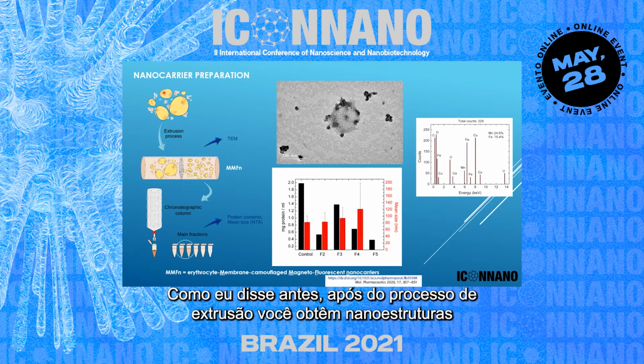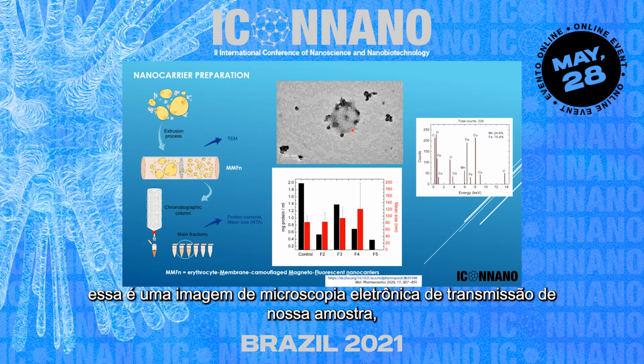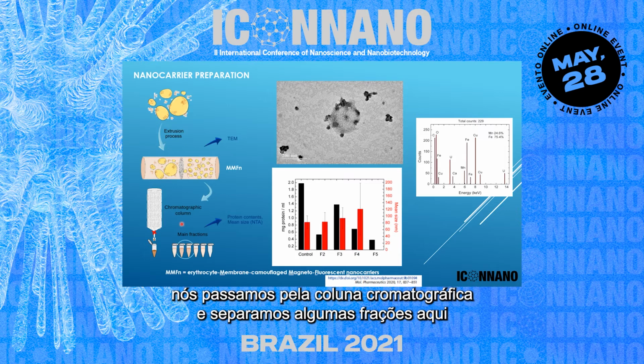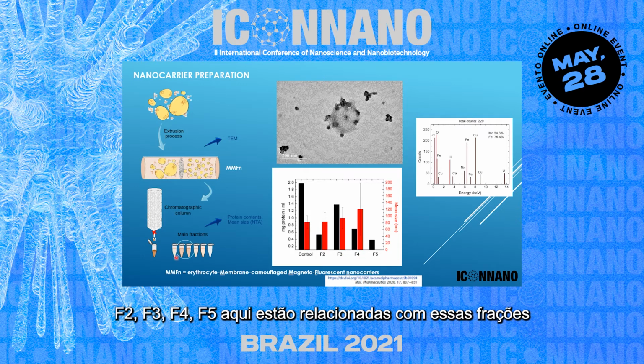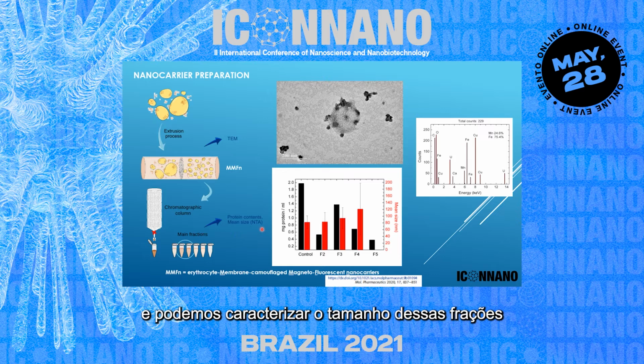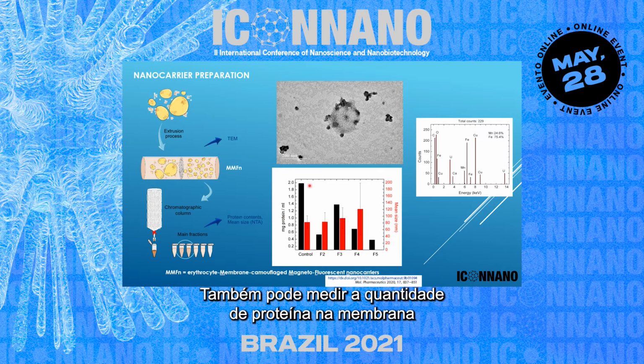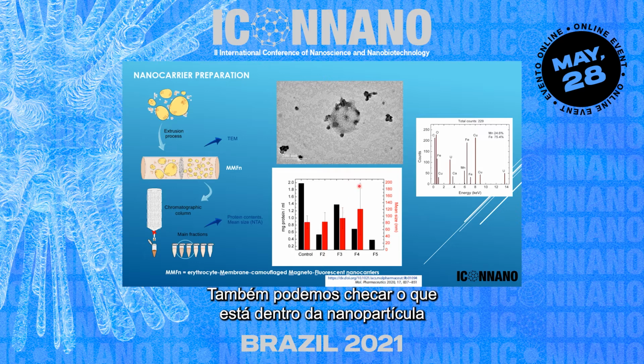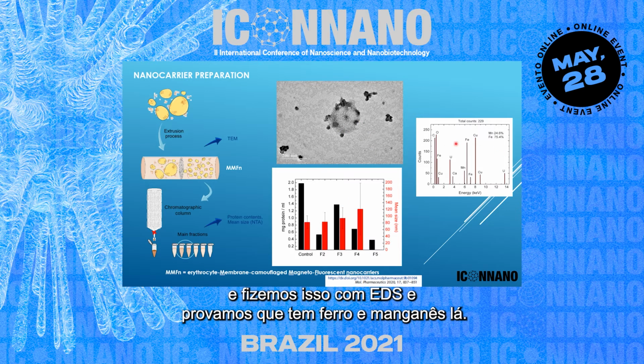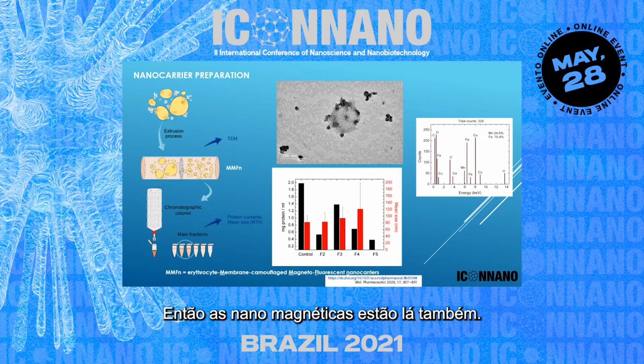So as I told you before, just after the extrusion process we obtain nanostructures. This is an image from transmission electron microscopy of our sample. We can pass through the chromatography column and then separate some fractions here. So F2, F3, F4, F5 are those fractions. We can characterize the nanoparticle size using nanoparticle tracking analysis, and we found around 100 nanometers. We can also measure the amount of protein that we have in the membrane. So you see that this is the control, this is the one with fraction three, and we can also check what is inside the nanoparticles, and we do that by EDS, and we prove that there is iron and manganese there. So the magnetic nanoparticles are there too.